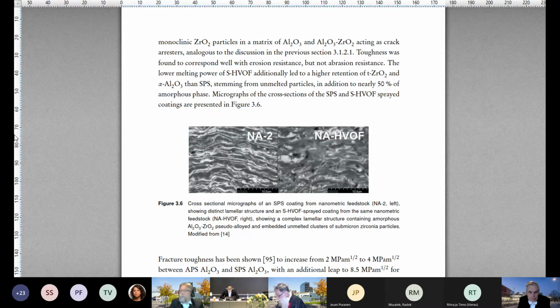Not really. I think in the right one of figure 3.6, there is the nano HVOF that has a lower temperature than the plasma spray coating on the left side. You could see these white clusters, that would be the zirconia, quite poorly embedded. It looks just like the coatings from one of my publications, where there are almost discontinuities of unmolten or poorly molten zirconia clusters. And inside that, you would probably find nanoparticles if you would zoom in. But then the benefit of these particles in this form is a bit of a question. Yeah, I agree.